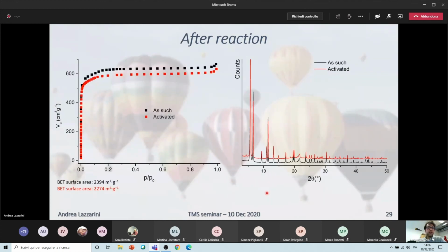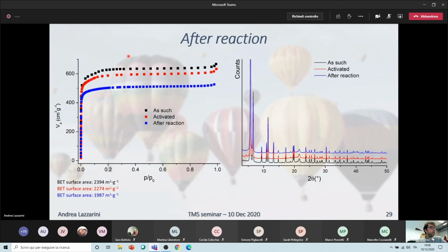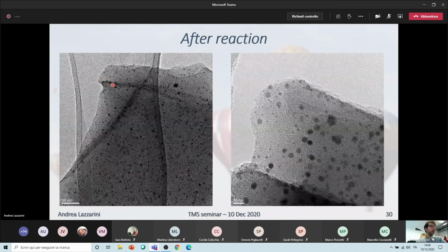And we also characterized the material after reaction, and we ended up with a slightly lower surface area because, of course, we have some degradation of the material, and mostly we have filled the cavities of the MOF with some metal nanoparticles that are reducing the surface area, as you can see from these microscopy images. But still, the system was cycled and was still active. And so this was a very good discovery from the group where I was working.